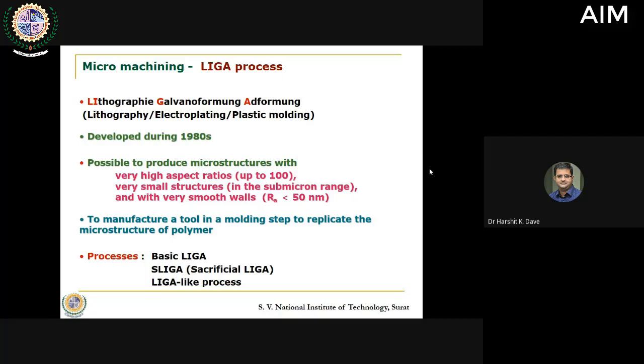Another process where lithography is used is the LIGA process. Here there are three different activities being simultaneously done. The lithography is done, electroplating is done, as well as plastic molding is done. So it is possible that this process is highly accurate. It is possible to go for very high aspect ratio. It is possible to go for very small structures in the sub-micron range, and you can get very good quality of smooth finished walls. If you measure the roughness of those walls, you get it somewhere close to 0.05 microns, 50 nanometers. So that is the level of accuracy that you may get. But again, this process is a costly affair.